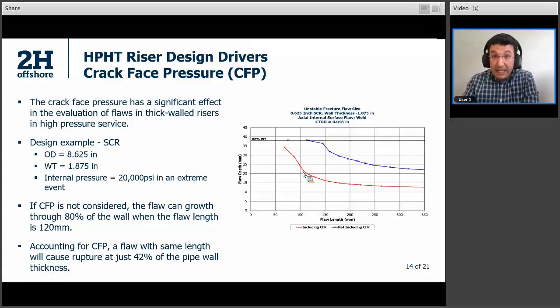Let's take an example of 80% wall thickness. If your flaw depth is around 80% of the wall thickness, your fracture flaw length is around 120 millimeter if you don't include the crack face pressure. But if you include the crack face pressure in your design, then suddenly your fracture limits go down. For the same flaw length of 120 millimeter, only 42% of the pipe wall thickness will be sufficient to stop the rupture. So that's another thing the designer needs to be careful about for high pressure systems.